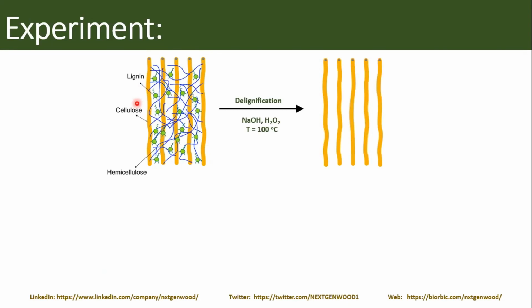And this treatment results in removing of lignin and hemicellulose, leaving just cellulose fibers. And we have lots of space between these fibers where we can put our ions, and then these ions will be like in a channel, in the nanochannel. And then we can also bring some charge to the surface of these cellulose fibers, and then we will have charged nanochannels. And this is very similar to what people were doing for thousands of years by producing paper, except we are trying to make the procedure very carefully so that we do not destroy the structure of natural wood.